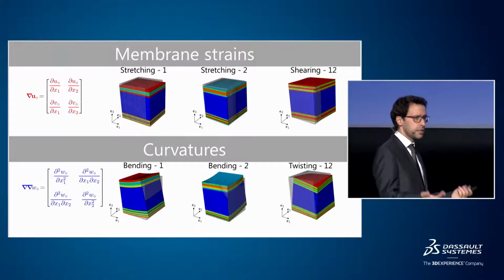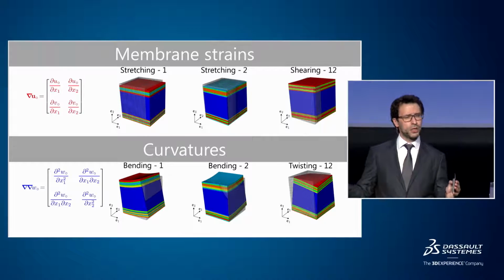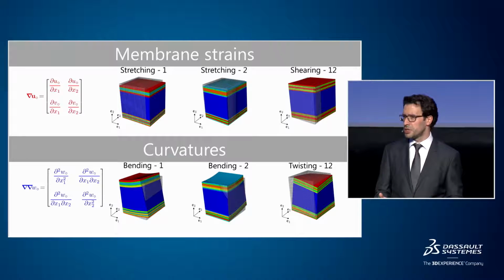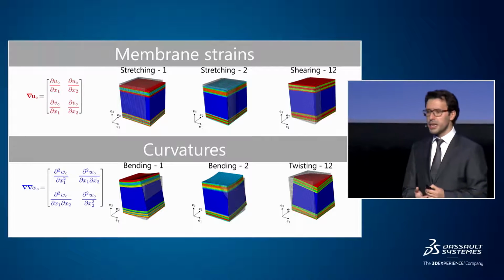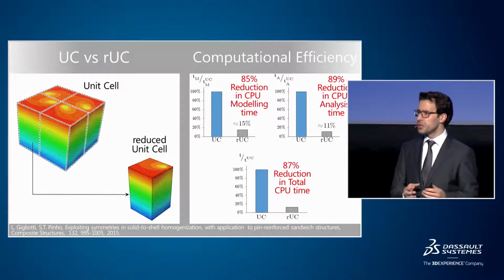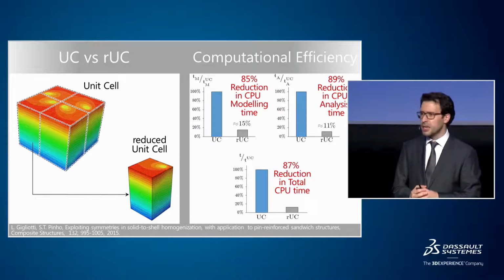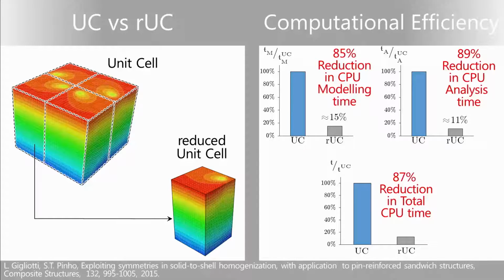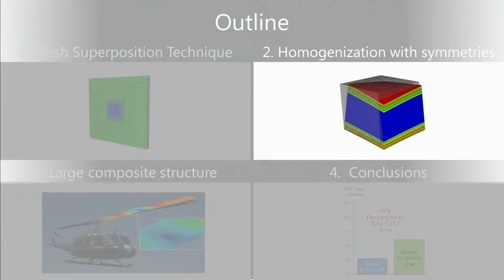So this is something that has existed for some time, so there's nothing new in calculating homogenized shell properties with unit cells. But what we've done was to use the symmetries in the unit cells so that instead of actually simulating an entire unit cell, we simulate, in this case, only a quarter of it by exploiting the symmetries that we have inside. And with that, we can, quite surprisingly, reduce the computational cost very considerably to 1/10 of what we would otherwise have. So that's the only thing that I wanted to say about homogenization.